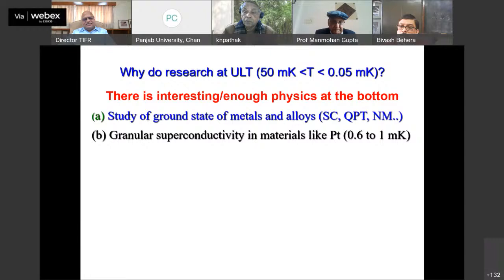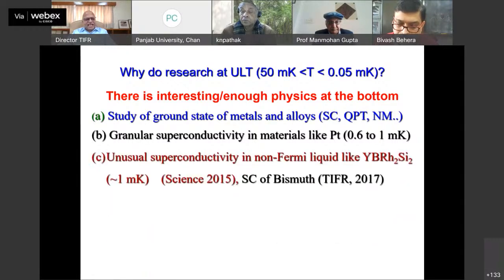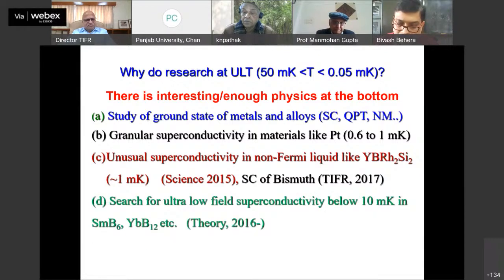Then superconductivity occurs in granular form. Platinum is not a superconductor down to the lowest temperatures people have reached. But in granular form, it does tend to show superconductivity at fairly low temperatures, from 0.6 to 1 millikelvin. Then you have very unusual superconductivity that happens in ytterbium rhodium silicon 2 at 1 millikelvin. And then the superconductivity of bismuth, which was a TIFR result in 2017. I'm going to talk about that later.